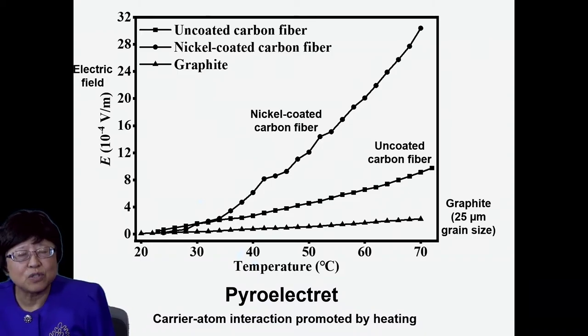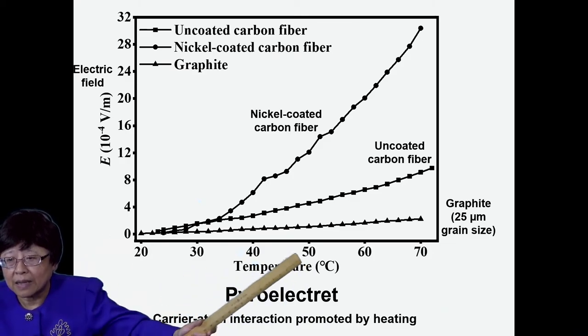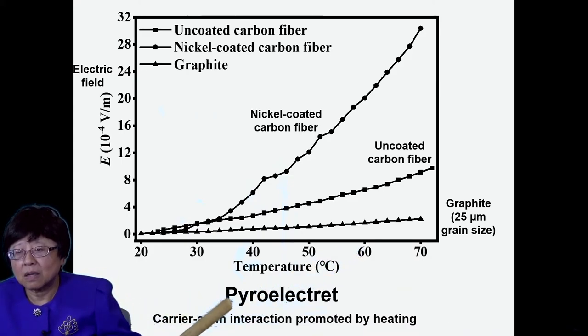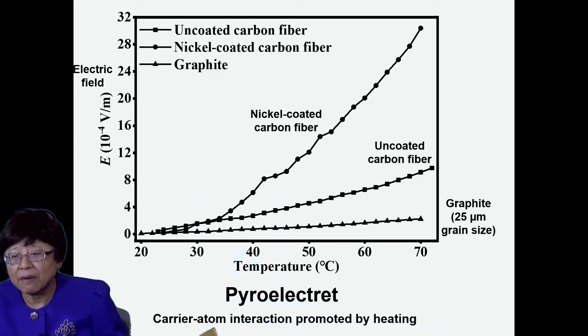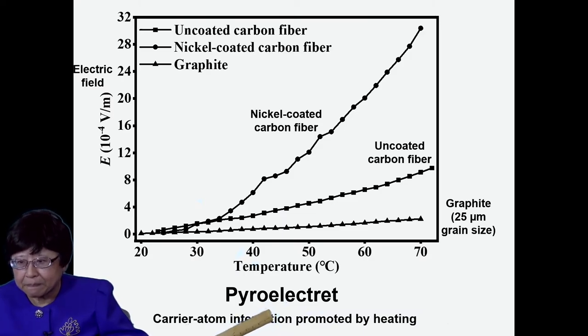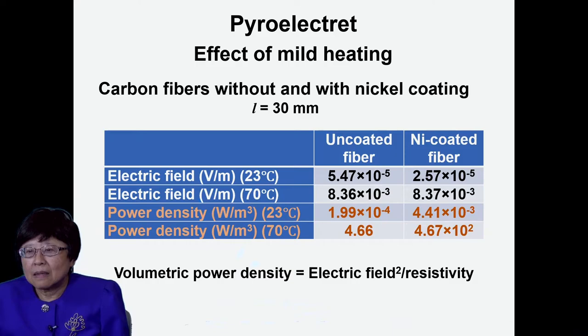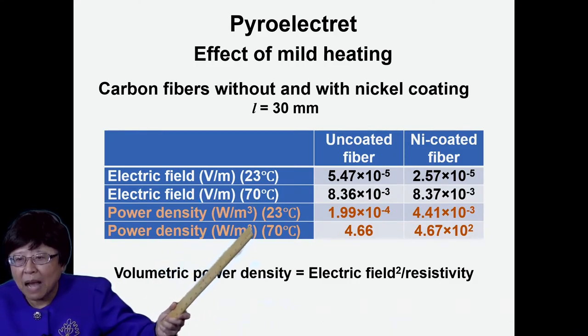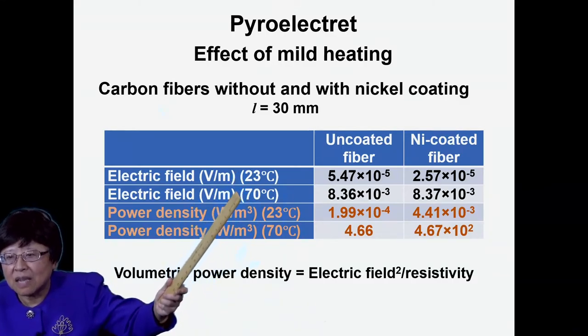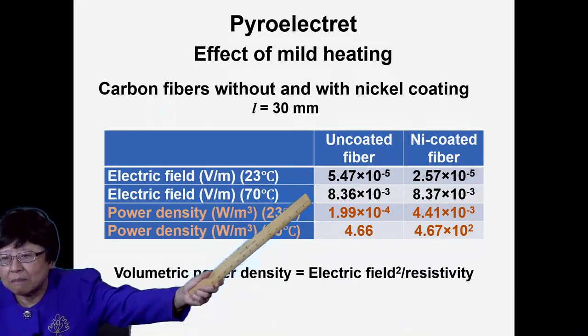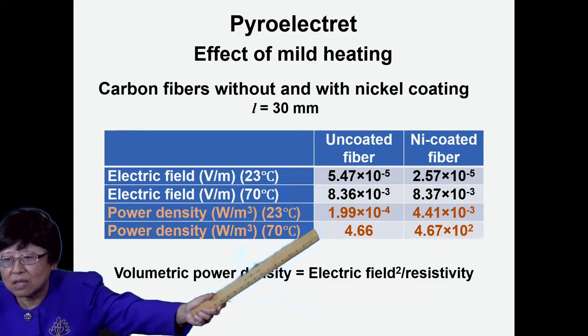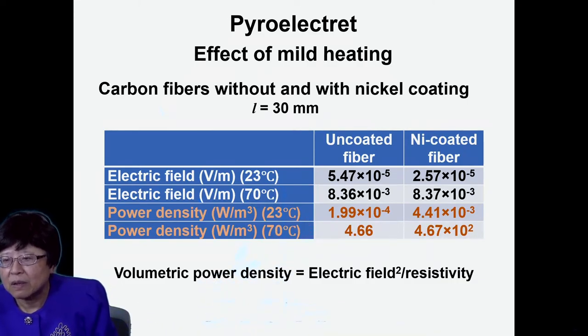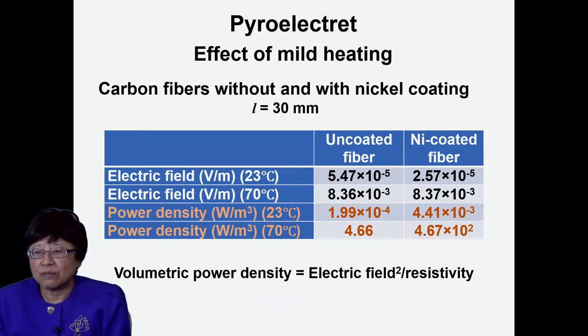So as I said, the higher temperature helps the electret, not just the permittivity. And this shows the electric field increasing with heating, again up to only 70 degrees C, and this we call pyroelectret behavior. That means the carrier-atom interaction is promoted by the heating. And because of the heating and the promotion by it, if you increase the temperature from 23 to 70 degrees C, you get much increase in the electric field and also much increase in the power density, whether for uncoated fiber or nickel-coated fiber. Note that the power density I talk about is the volumetric power density, which boils down to the square of the electric field divided by the resistivity.